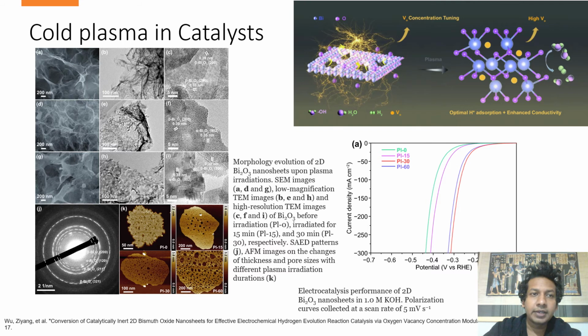In this work, catalytically inert 2D bismuth oxide is activated by cold plasma for hydrogen evolution reaction. The tuning of the oxygen vacancy by cold plasma resulted in an HER catalyst with lower overpotential, high exchange current density, and excellent stability. This work thus paves a way to activating inherently inert metal oxide materials into high-performance electrocatalysts via cold plasma-assisted modifications.